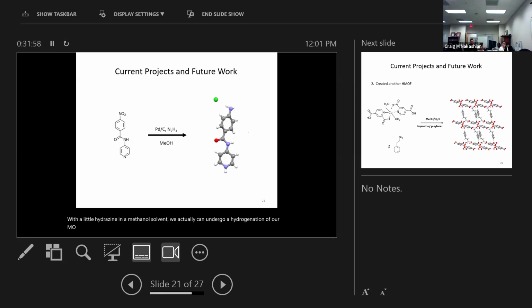And now you see in our crystal structure, remember, oxygens are red. Now we have the NH2, and the hydrogens are our white spheres. So we actually have undergone the reduction of our molecule. But the only problem I've had with this project, and I've tried a few different directions, is that we generate a pyridinium chloride. So now our pyridine molecule is positively charged. It picked up a proton, and we have a counterion chloride that's free and dissociated. So always a drawback on everything.